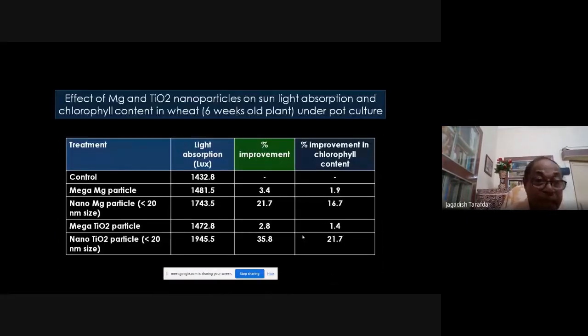So now, another important thing we find is that magnesium and titanium dioxide nanoparticles are helping sunlight absorption by the plants. You see, with the same amount of chemical fertilizer, only 3% improvement of light absorption, whereas nano magnesium 21% improvement. Titanium dioxide, similar mega particle 2% and nanoparticle 35%. So you know that more improvement of light absorption means more chlorophyll content. So we are getting more chlorophyll content in the leaf also.